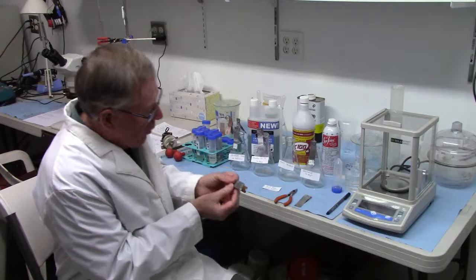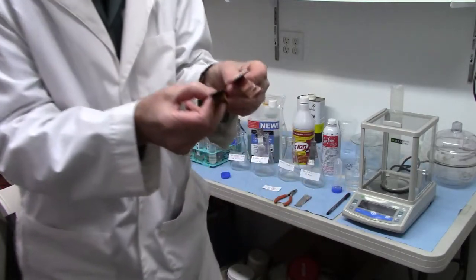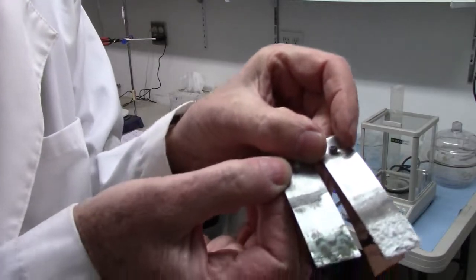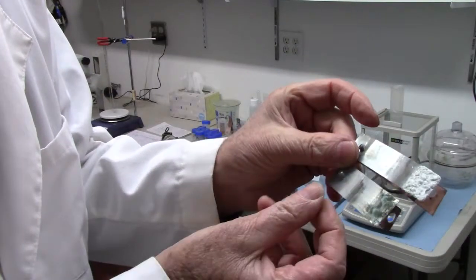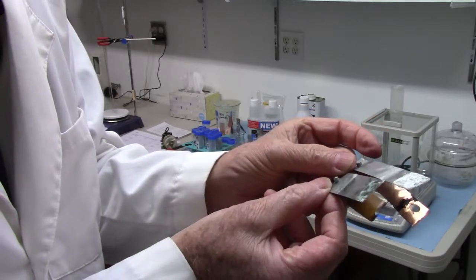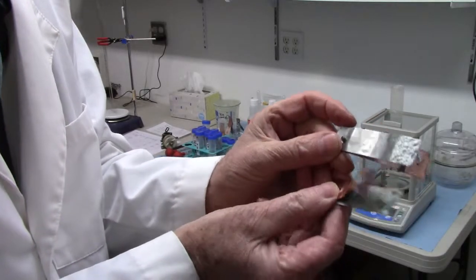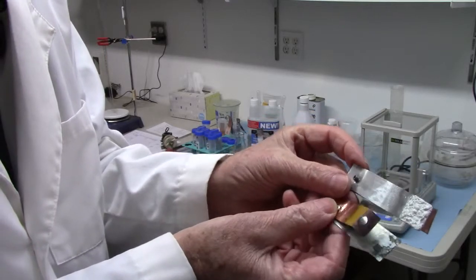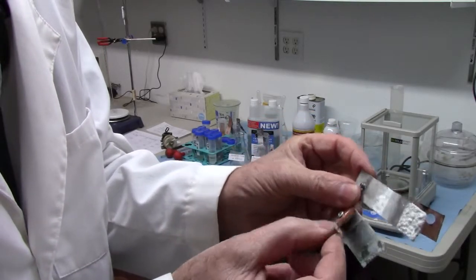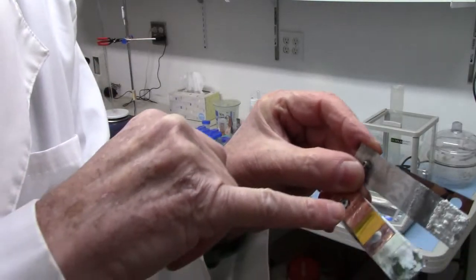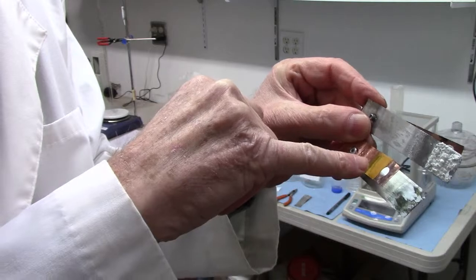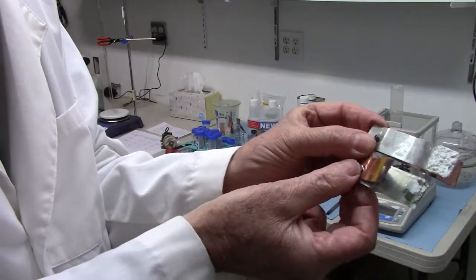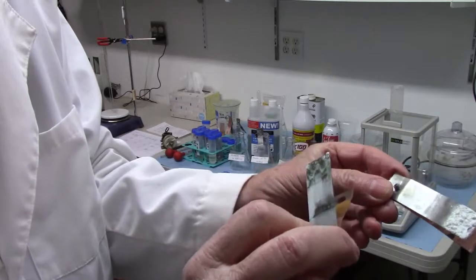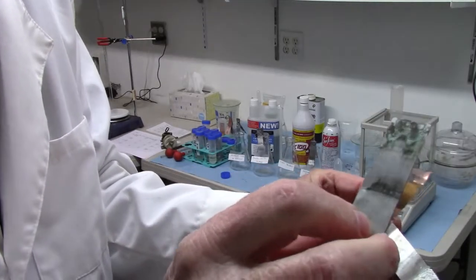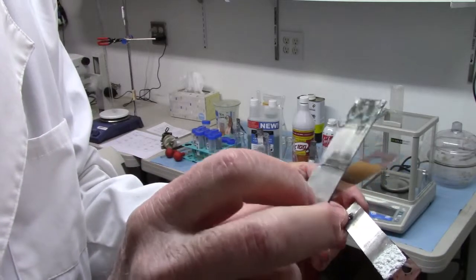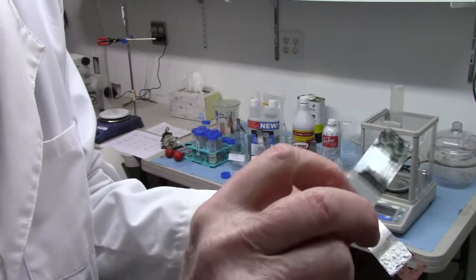And here is the K100 compared to the blank. There is the K100. It has blue deposits on it. And what that means is that the copper has been dissolved into the solution and has redeposited on the zinc. You can see the attack on copper. That's that orange colour. That's what's happened there. Some of the copper has dissolved and deposited on the zinc. That's why the deposits there are a greenish, bluish colour. Hope you can see that.